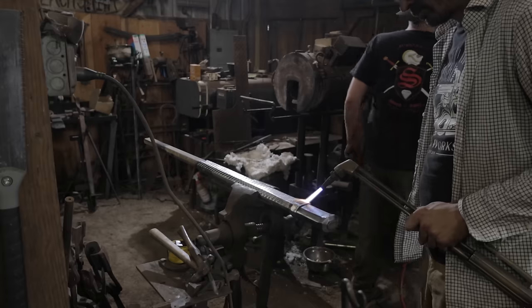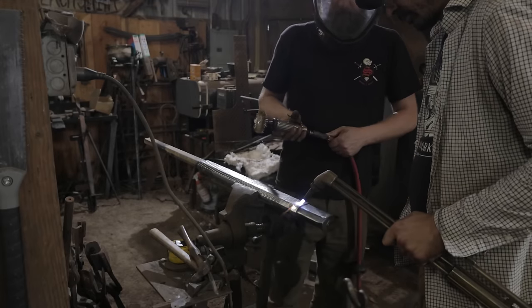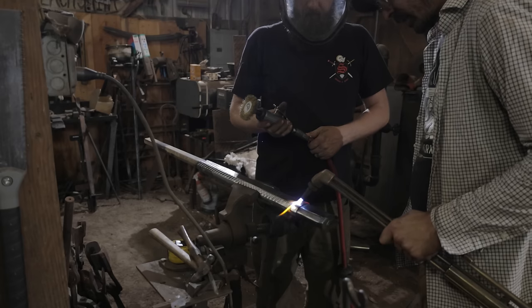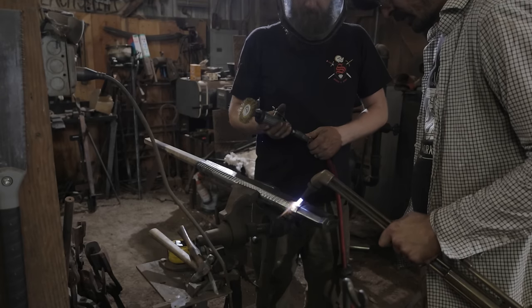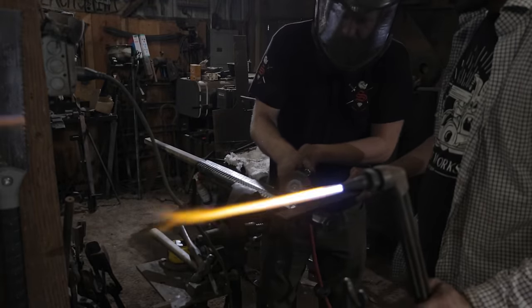We actually made some of the parts that should be brass out of steel so that we could weld them and attach them solidly to the other steel parts. To turn them brass, we use a little bit of heat from a torch and a brass wire wheel that deposits the brass onto the surface of the steel, leaving the yellow color.